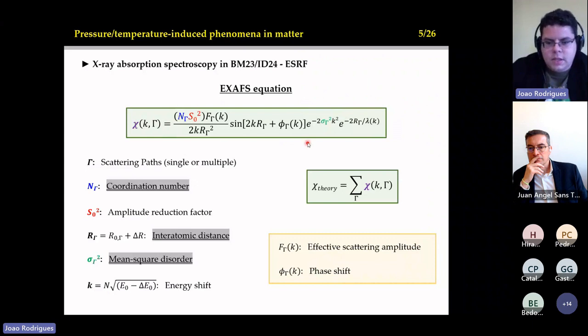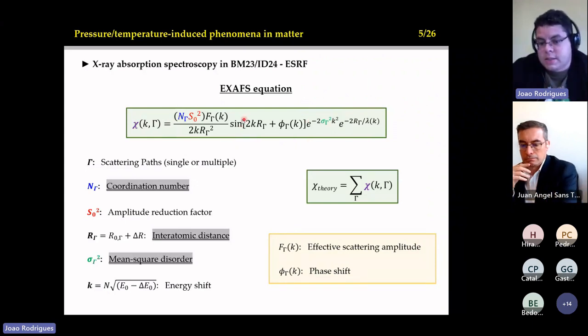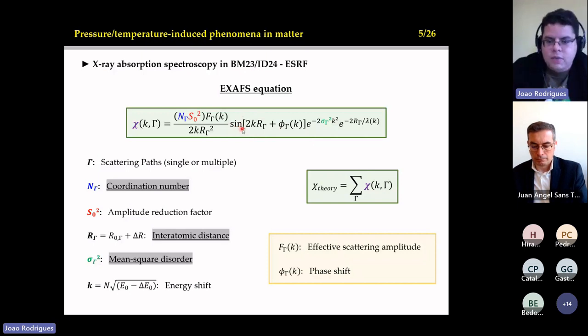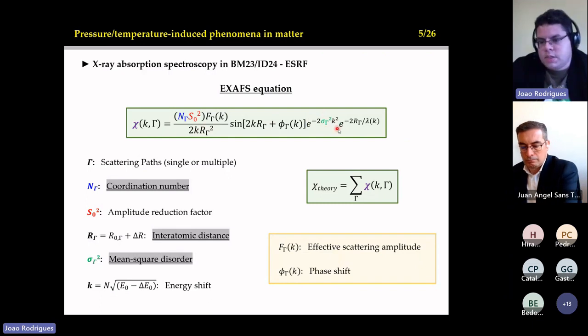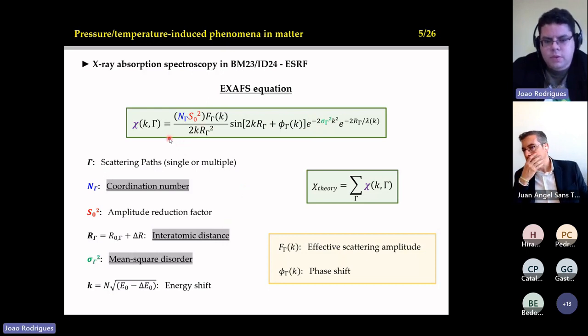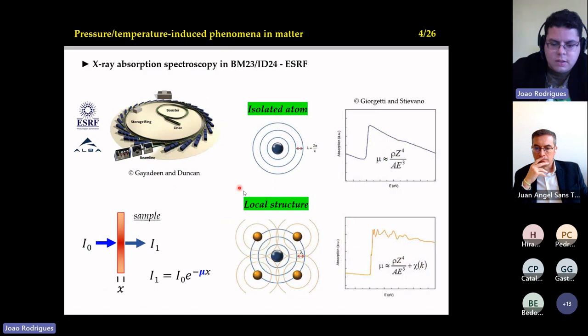It seems a very big equation, but in the end it's very easy because it's an oscillation. So there is a sine wave here, and there is a frequency, which is the distance for us. But these oscillations are also governed by a wave, which is a three-dimensional wave, and that's the reason we have this term here, squared for the distance. And we have localization, which is related to sigma squared, the disorder parameter. Since you have your signal from the X-ray absorption, you can determine from the fittings the coordination number around the target atom.